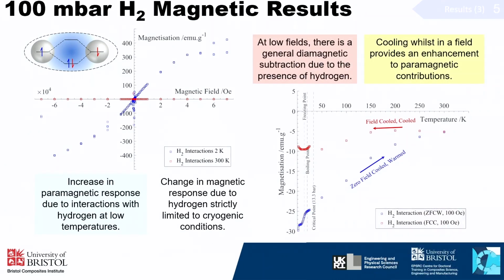If we look at the magnetization versus temperature data, we can get a little bit of an insight into what's happening. If we start down at the bottom there, down at 2 Kelvin, and warm up, we can go through various phase changes of hydrogen, which we can detect using SQUID magnetometry. As we go through the gaseous phase, we start to desorb from the surface. But upon cooling it back down with an applied field, we end up with a different pathway as we come back down. And as we get down to that solid stage, at really low temperatures below 10 Kelvin, what we see is this inflection up into a paramagnetic state, which again was quite unexpected, showing some sort of interaction is occurring in our sample.